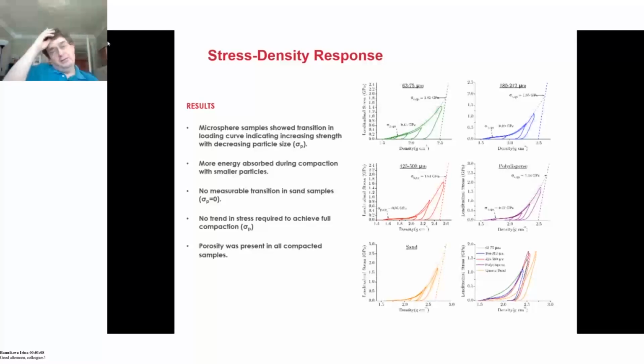Microspheres showed increasing strength with size. More energy was absorbed in the compaction with smaller particles. Sand, basically, there was no real transition seen in the sand samples. So it just started compacting from the beginning. And there was no trend in stress required to achieve full compaction in the systems. But porosity was present in all of these samples.